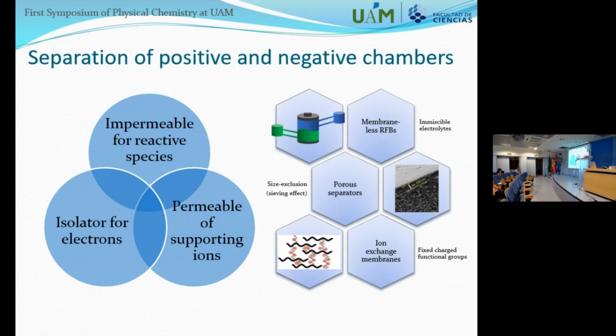Then we have the porous separators, which are based on the size exclusion effect, or sieving effect. This means that, because we have this separator in the middle, depending on how large the pores and channels in the separator are, they may or may not allow the conduction of some of the ions. So these pores have to be small enough to prevent the crossover of the active species, but large enough to allow the crossover of the supporting ions.